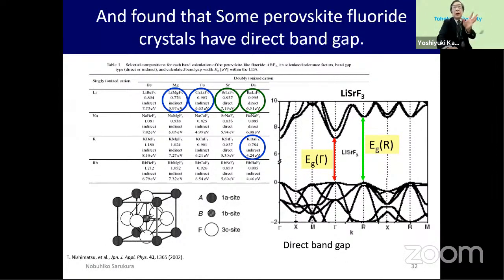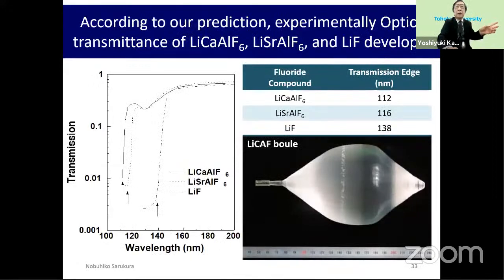Good means direct band gap and wider band gap. And these are the very good materials, for example, lithium calcium aluminum fluoride, and so on. So experimentalists really synthesized these, and it is a material having a very wide band gap and a direct band gap. So they made these as commercialized material, and actually these materials are used. So in 10 years, we computed and predicted new good VUV material for experimenters, who synthesized and commercialized it.